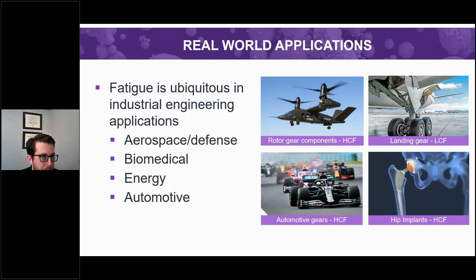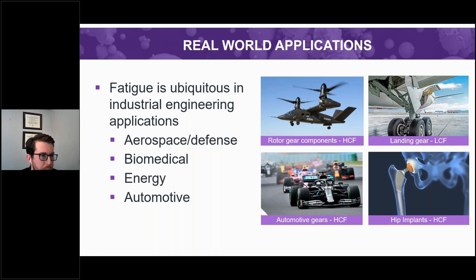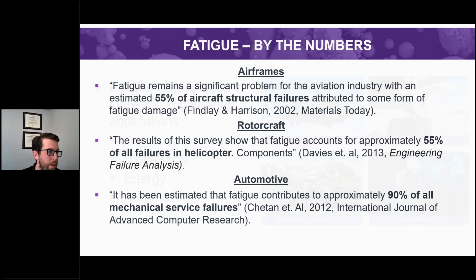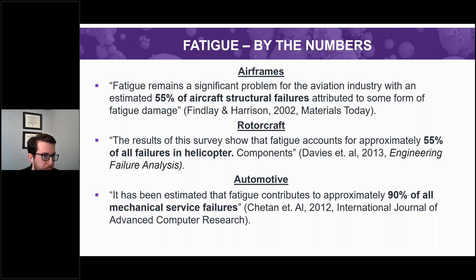Both high-cycle fatigue — for gears in helicopters, cars, or hip implants that see loading cycles for every single step you take — and low-cycle fatigue, for something like a landing gear that's only loaded once per flight, need to be modeled differently, but ultimately drive the performance of engineering alloys. Looking at the literature, it becomes clear that across many industries fatigue remains the number one cause of failures — from airframes and helicopters citing 55% of all failures being a result of fatigue, to automotive citing 90% of all mechanical service failures being a result of fatigue.